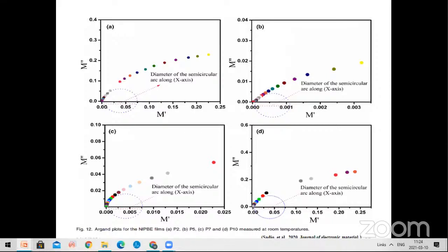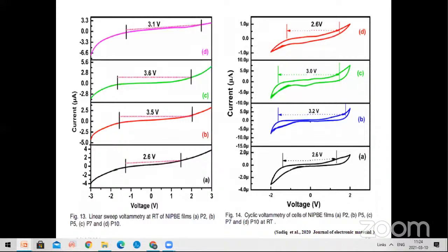And also we have the modulus study. In the modulus study, we find some semicircular arcs in the beginning. That is why we think this gives more information about the conduction mechanism. And we also did the cyclic voltammetry study. This cyclic voltammetry study is to find out the voltage stability of these polymer electrolytes. As we increase the concentration, the stability of the electrolyte increases.